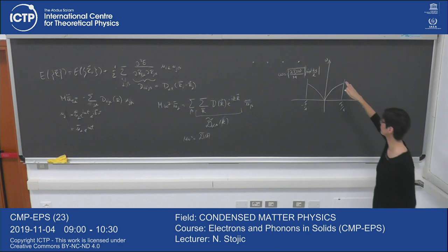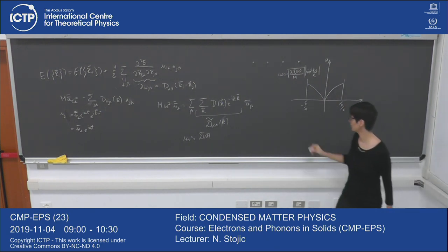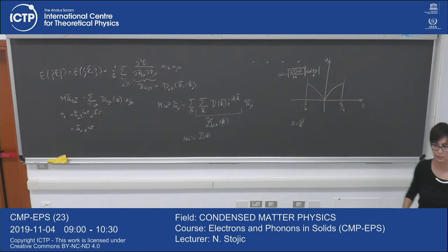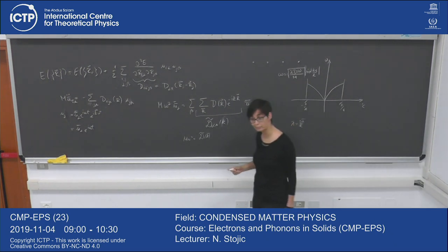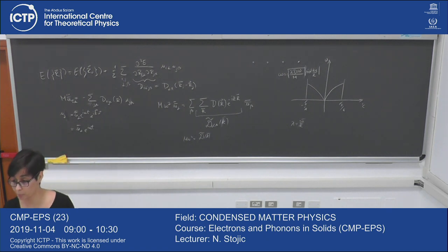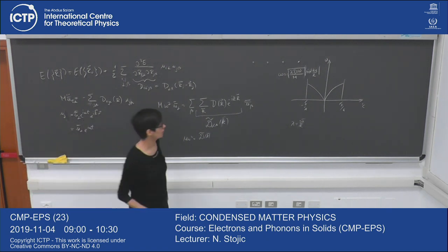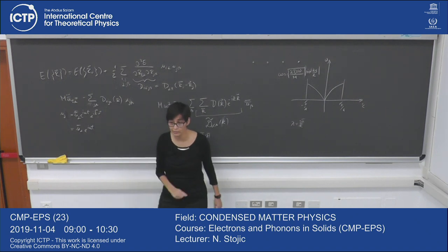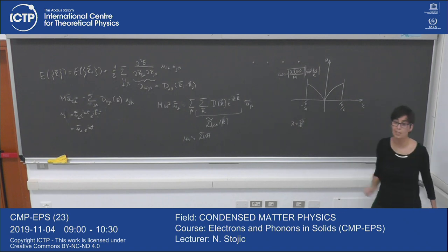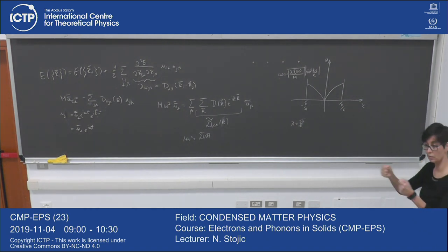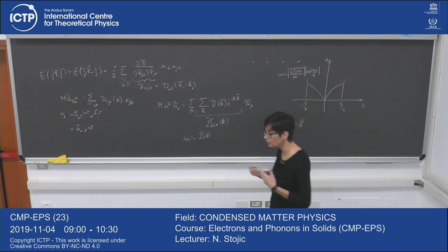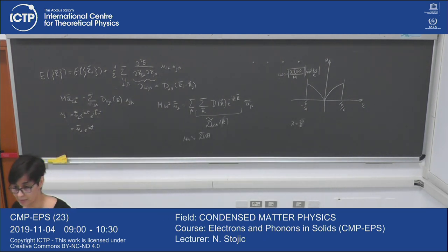And then we looked in the limit of k going to 0. We said that the wavelength is inversely determined by k, which means that here you have very long wavelengths. And the waves with macroscopic wavelengths are sound waves that you can see. Then you can see, plugging k to 0 in this formula, that they all have the same amplitude in this limit. So they're moving as the center of mass, translational motion. The whole crystal vibrates together in phase. So the sound is a collective vibration of the atoms in the crystal. It's a collective phenomenon.